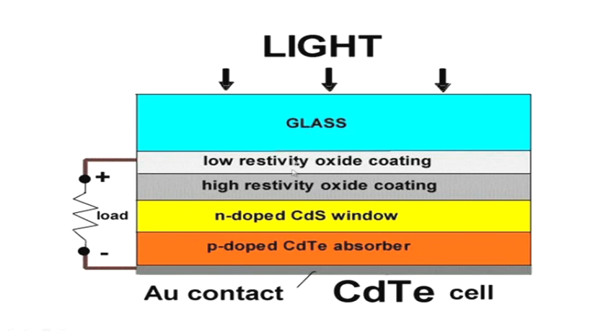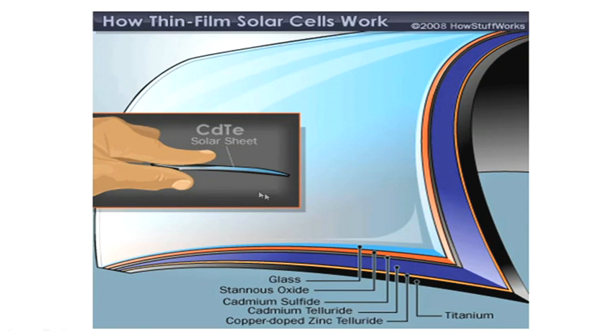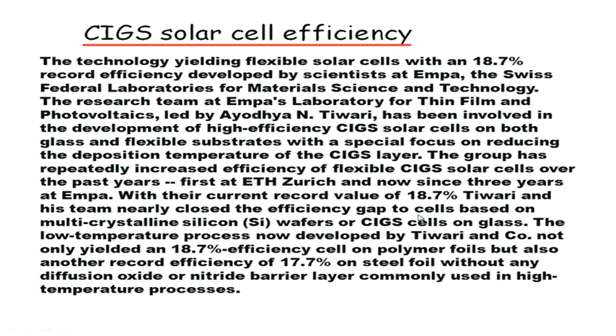So different types of structure are used, and you can see that it has the flexibility to be grown on glass. It has the flexibility to make use of a particular semiconductor, in this case the cadmium telluride emitter, and it has a higher absorption coefficient. However, 14%, 15% or a maximum of 17% is the efficiency reported for this kind of solar cell. Here we can make use of a flexible substrate also. Another material can be copper indium gallium selenide, CIGS, and almost 18.7% efficiency has been obtained.